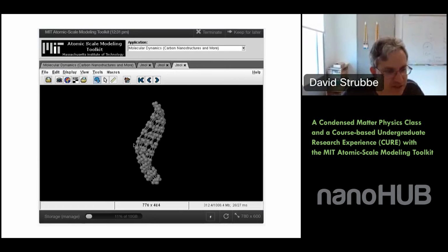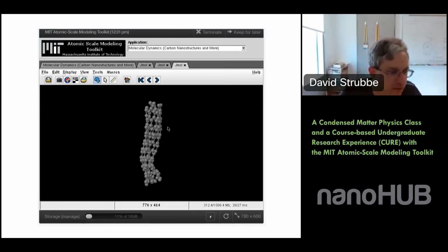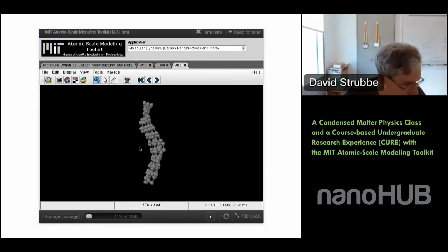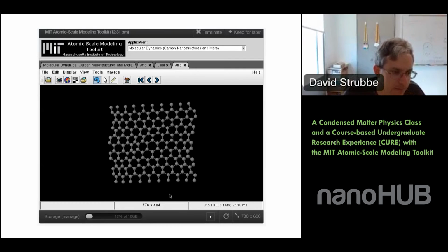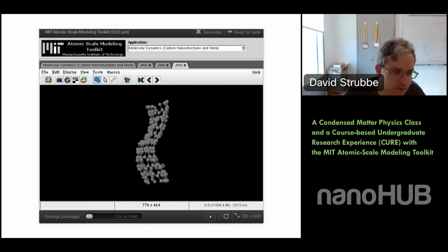You see how much things are bending here. Ahmed is asking about the effect of this bending. This is related to the Mermin-Wagner theorem, which says basically that you have instabilities in a 2D material. That also applies to magnetic order and other things like that. And there are all kinds of rippling effects that people have seen in 2D materials, which are interesting, right? You can see it's very dramatic what's happening at 2400 Kelvin.